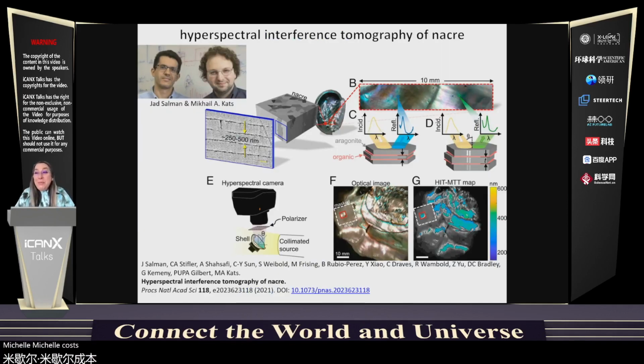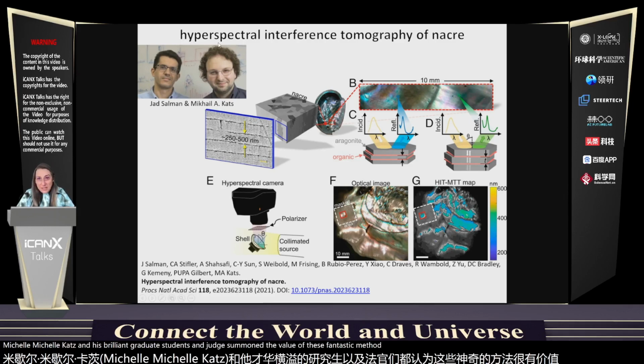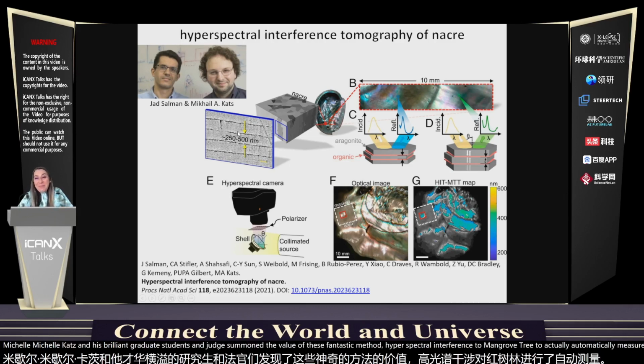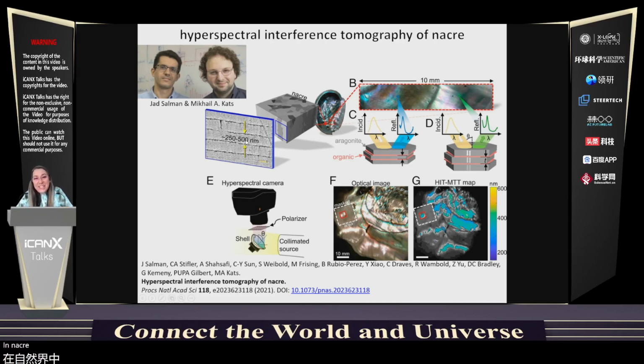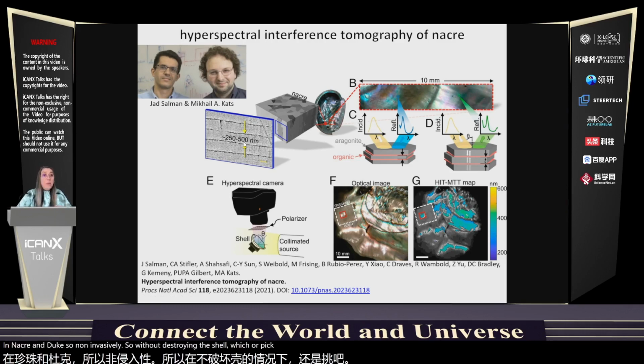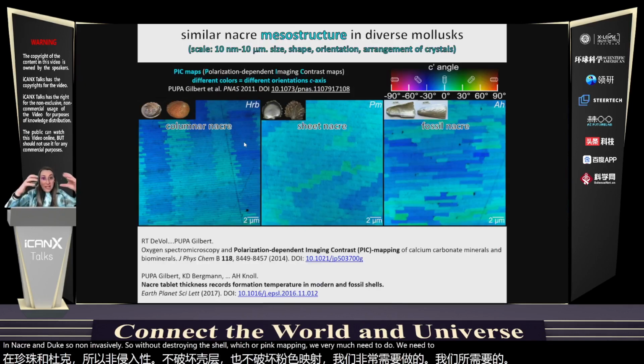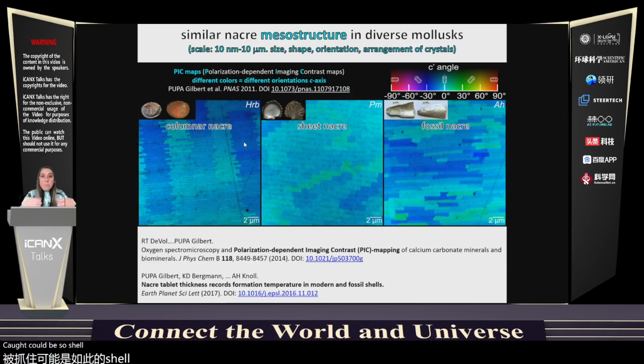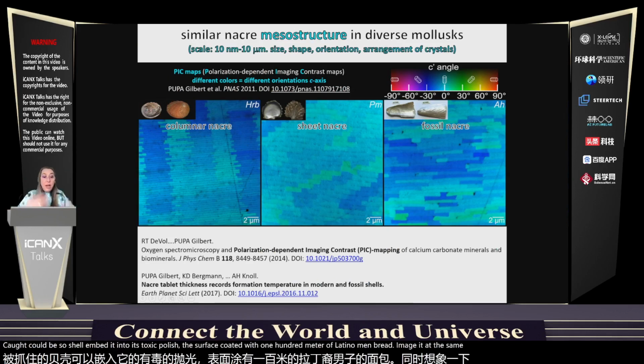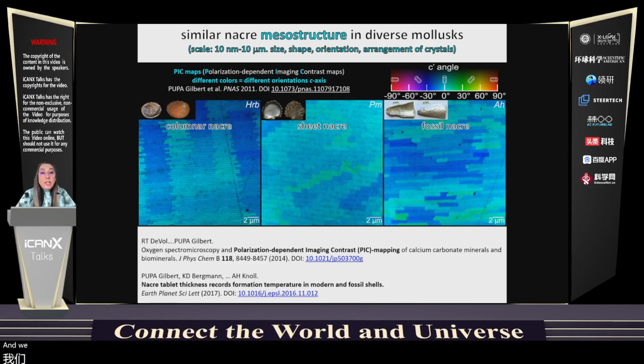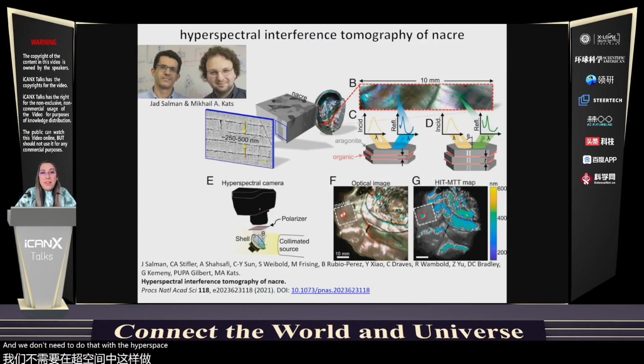Mikhail Kats and his brilliant graduate student Jad Salman developed this fantastic method, hyperspectral interference tomography, to automatically measure the tablet thickness in nacre and do so non-invasively. So without destroying the shell, which for PIC mapping we very much need to do: we need to cut a piece of shell, embed it into epoxy, polish the surface, coat it with 1 nanometer of platinum, and then image it at the synchrotron. We don't need to do that with the hyperspectral interference tomography.